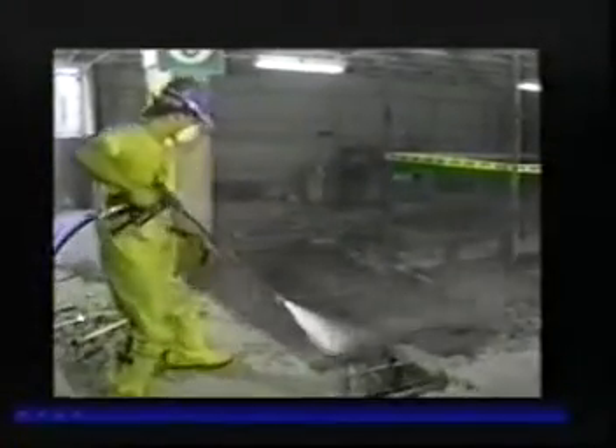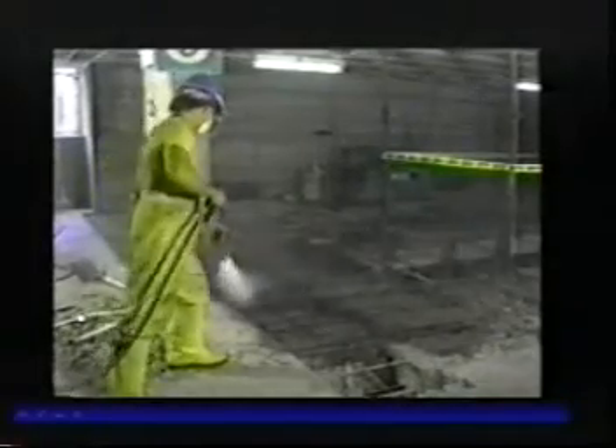You can see here the saw cut was made, and we're cleaning it up with a 15-pound chipping hammer. We also, in these guidelines, recommend not to exceed 30 pounds in weight of the chipping hammer. This is a 15-pound hammer that was shown there. Many times contractors will use up to a 30-pound to pre-break down to the reinforcing steel. These are some examples of using hydro demolition for the removal. Once all the removals are done, cleaning is required to remove the dust and debris and any bond-inhibiting materials. This is an abrasive blast that you're seeing here. And this is about 3,000 psi water pressure, which is the minimum required to do the same thing.